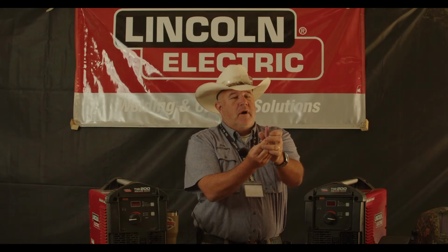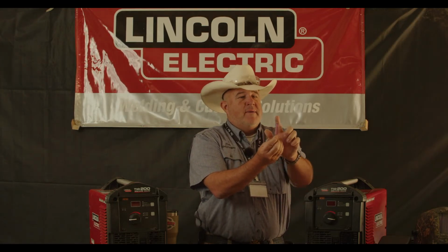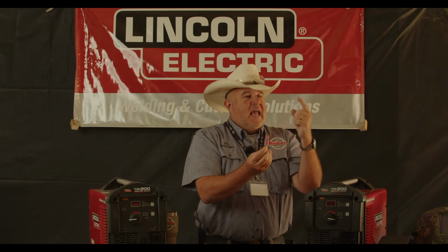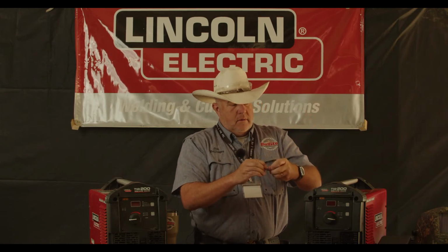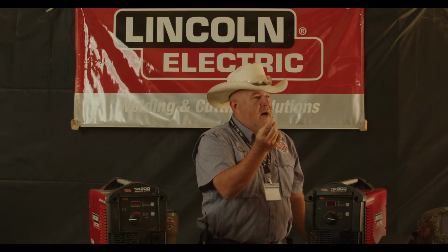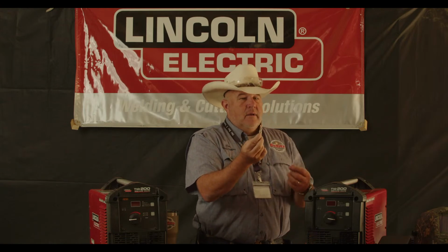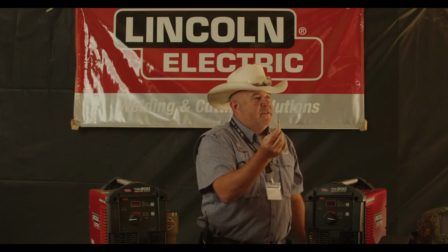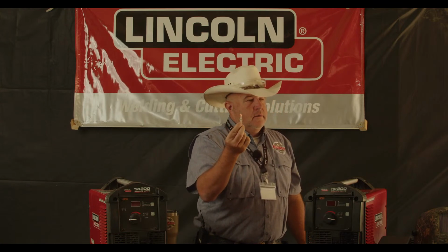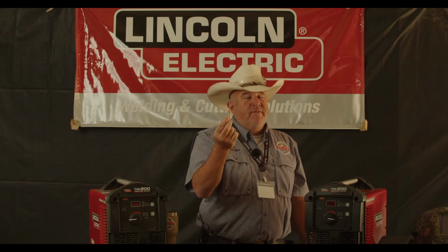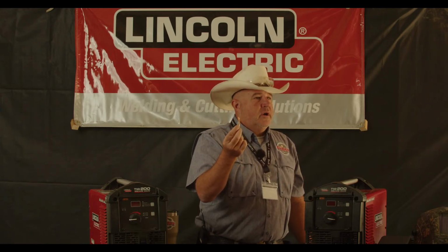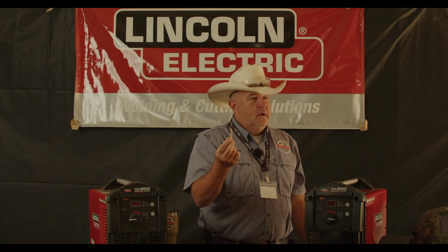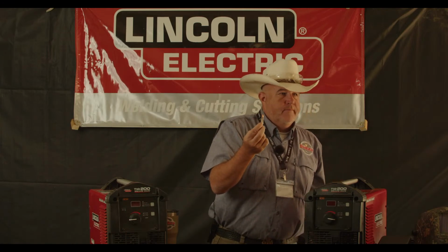There's a ceramic on there. That ceramic forces that gas to come out here. It cools this copper before we use it for welding, and it protects that tungsten from the atmosphere. That tungsten can get up above 5,000 degrees when we're welding. If it touches the oxygen even for a second, the tungsten is junk. I mean, we gotta go clean it. You can't use it for welding anymore.